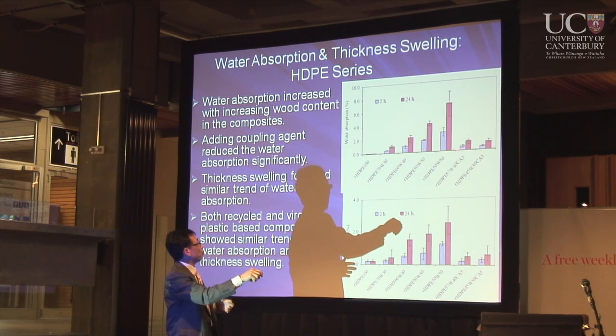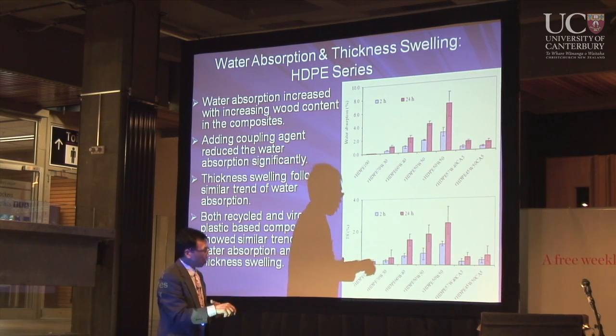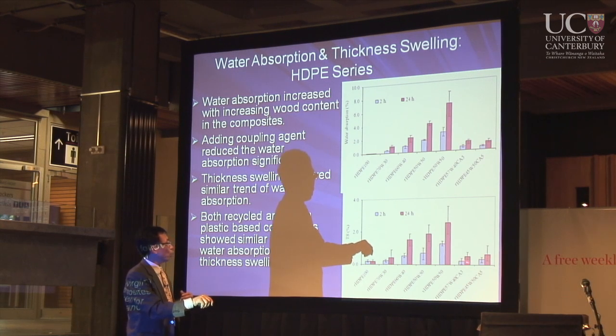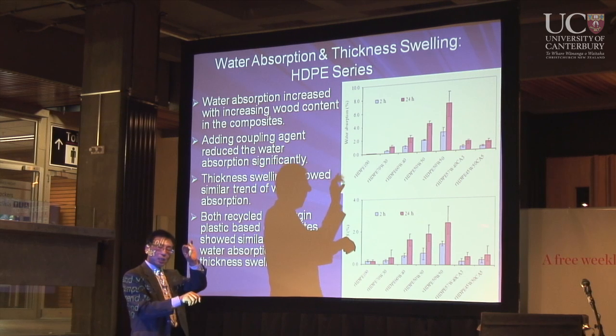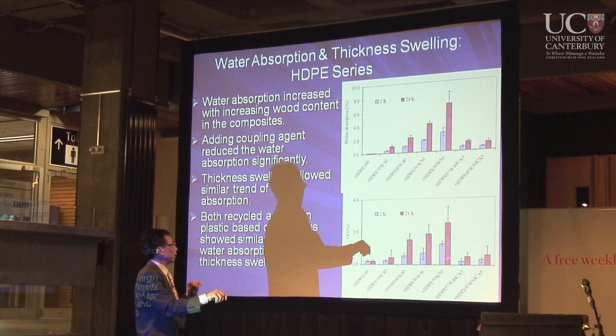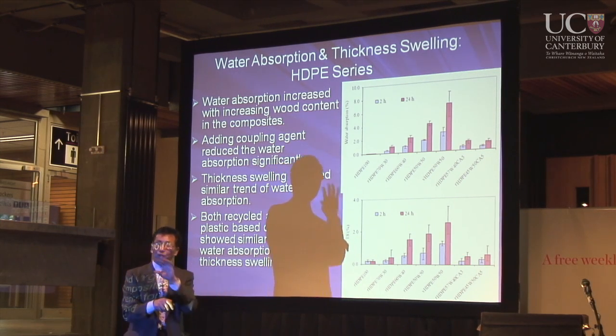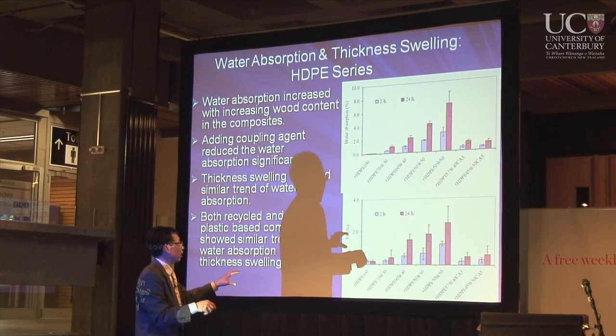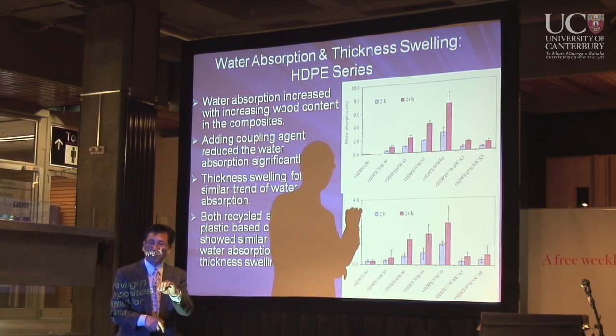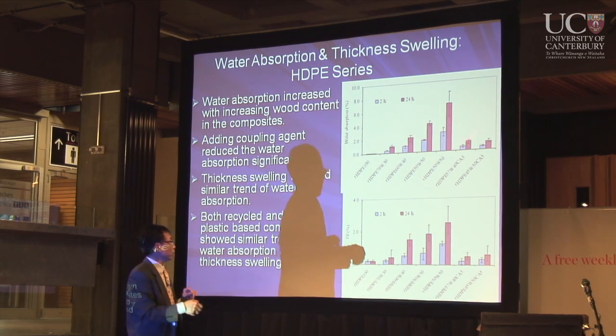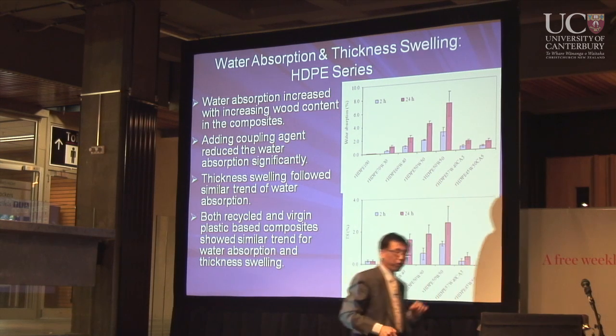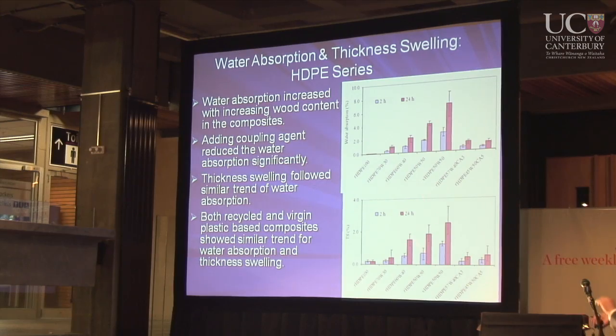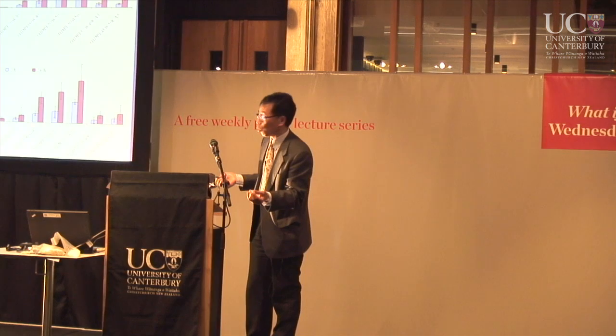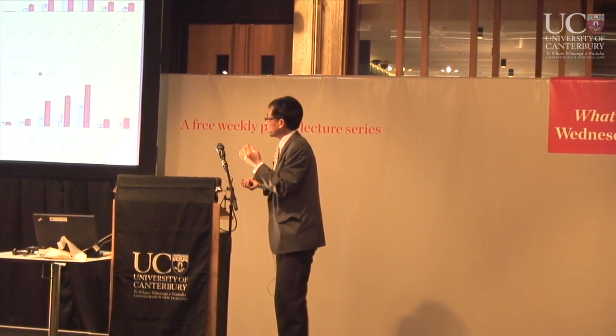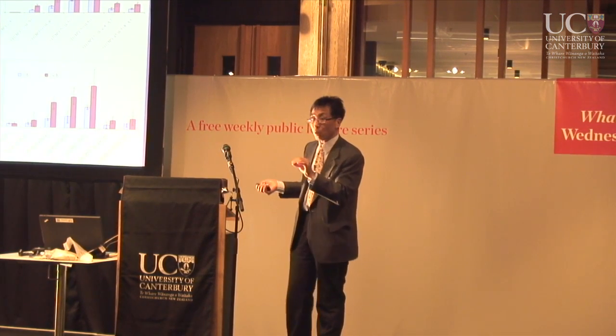So you can see this is a very small water absorption. And correspondingly, if you have less water absorbed, the thickness swell is quite small. You can see almost 0.5%. As I mentioned, if you put real wood in the water for 24 hours, you get at least a 3 to 5% increase in the thickness direction. So you can see this is much smaller swelling. It's much more stable. So from this result, we can see the material is quite stable, right? It absorbed much less water, and the thickness swelling, the dimensional change, is much smaller than wood.